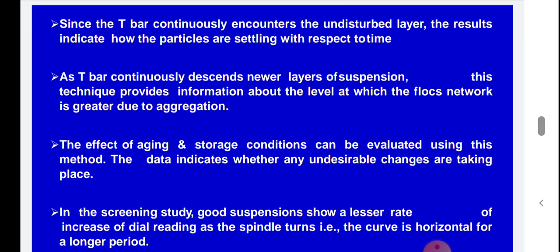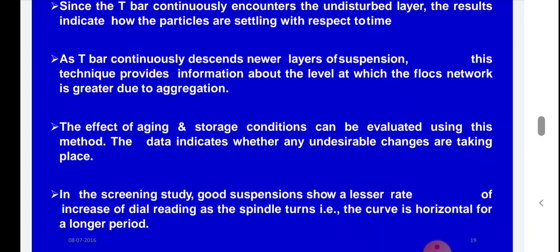Since the T-bar continuously encounters the undisturbed layer, the results indicate how particles are settling with respect to time. This technique provides information about the level at which the floc network is greater due to aggregation. The effects of aging and storage conditions can also be evaluated by this method. In the screening study, a good suspension shows a lesser rate of increase in dial reading as the spindle turns, and the curve is horizontal for a longer period of time.